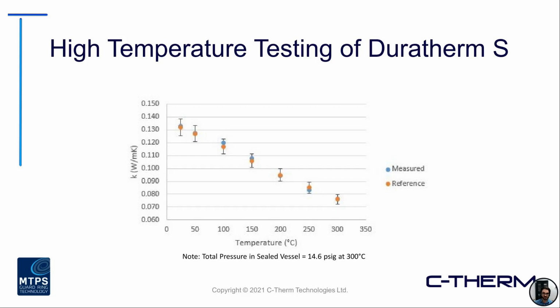We see here just some example data collected with the MTPS high pressure cell on a Duratherm material. This is a heat transfer fluid. You can see the trend in thermal conductivity as a function of temperature. Really good agreement between the measured and reference values, but just noting that the pressure of the sealed vessel was introduced in this testing. So we made note of that pressure and continued with the analysis under those representative conditions. And if this was something you're just testing in the ambient atmosphere, other issues can come into play as well, but also you may not be getting truly representative test data.